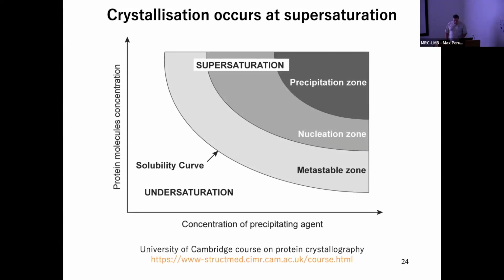Here is a 2D protein solubility phase diagram where saturation levels are represented according to the two main parameters that alter the protein solubility, because crystallization occurs at supersaturation. The sample and precipitant concentrations are the two parameters here. The solubility boundary curve divides the diagram into two areas, undersaturated and supersaturated. The supersaturated area comprises three zones: metastable, nucleation, and precipitation zones. So that's how we represent the phase diagram for protein crystallization.